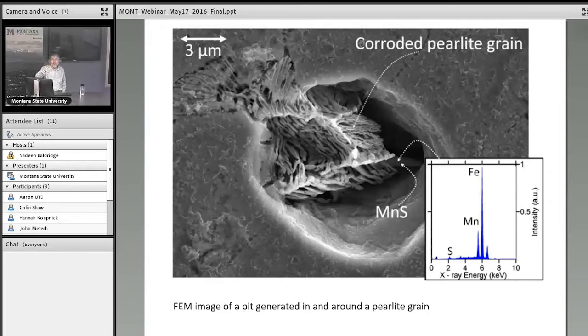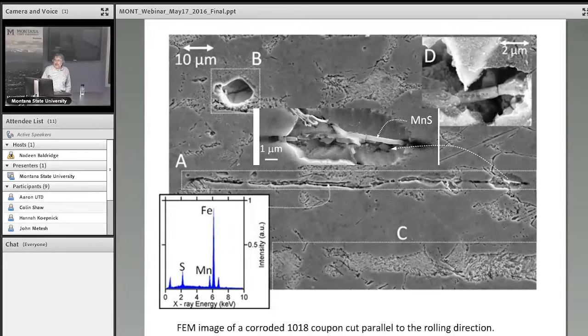Here's another thing in the data. This is again a parallel surface. You have this manganese sulfide inclusion running parallel to the surface, hundreds of microns. But I have here an enlarged view of this and another one here. Look at that, the manganese sulfide is broken right here. And here, broken at this location and at this location. So what happened is that during the metallurgical processing of this material, these manganese sulfides are just produced as a matter of metallurgy. And then they're hugged by this iron matrix all the way through.